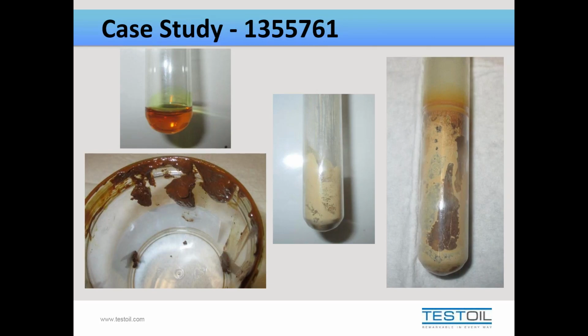And glycol and hydrocarbon fluids are known to not always be compatible, and this type of sludgy, sticky material is expected to result in deposits and impair the machine condition or machine operation. This type of deposit is also known to plug filters. So really, this was another system where it was recommended that the system needs to be flushed because there is really no other way to isolate out the glycol from the original hydrocarbon-based lubricants. Also, they needed to identify how glycol was getting into the system in order to prevent the contamination in the future.